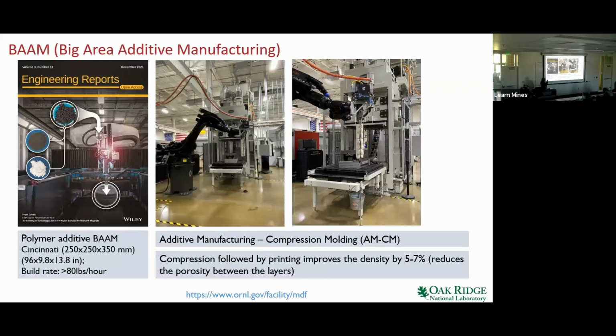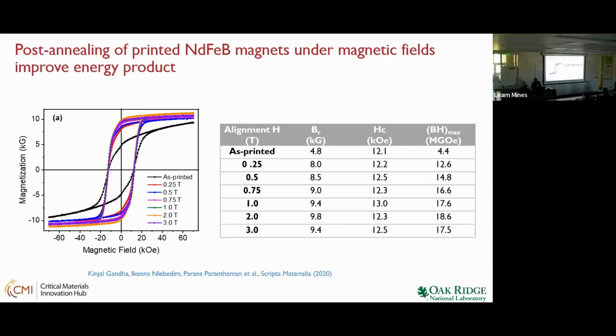If you compress it in a press while it's hot, before it's cooled, you can really improve the density by 5 to 7%. So the new method we call additive manufacturing followed by compression molding. That's a process we have been doing very lately and getting good properties.